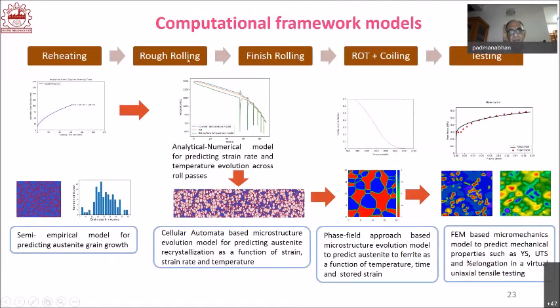And then when it comes to rough rolling and finish rolling, you have cellular automata based microstructure evolution models that can be used, because we know as a function of deformation how the shape changes. And also, once you know the composition, it will be possible for you to predict austenite recrystallization as a function of strain rate and temperature.